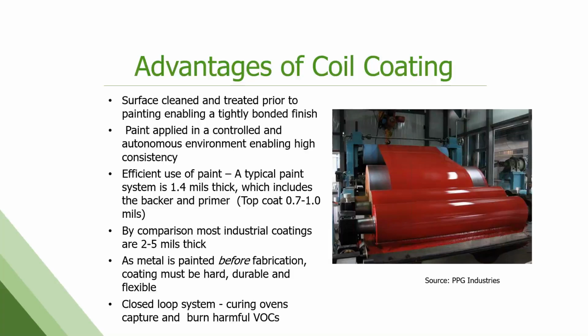Typically, the total paint system, including backer and top side, is only about 1.4 mils thick. This is very, very thin compared to most industrial coatings, which are 2 to 5 mils in thickness. Cars are usually 5 to 8 mils in thickness in coating. As a comparison, your average copier paper is actually 2 to 3 times thicker than the paint that we're putting on these substrates.